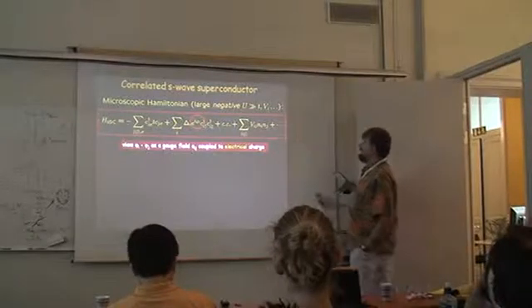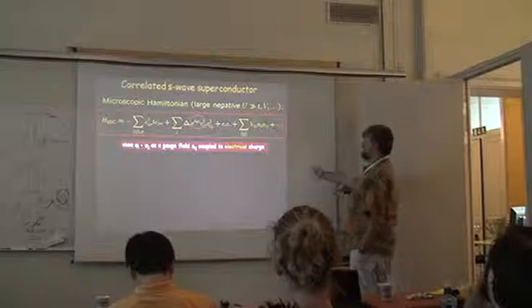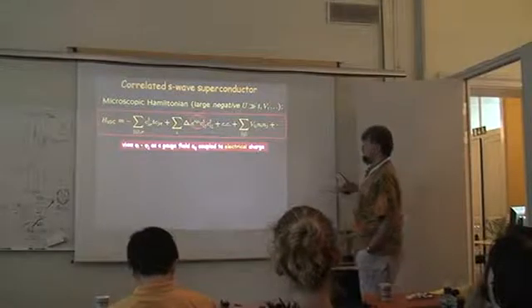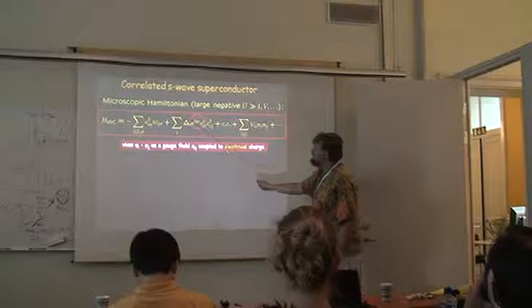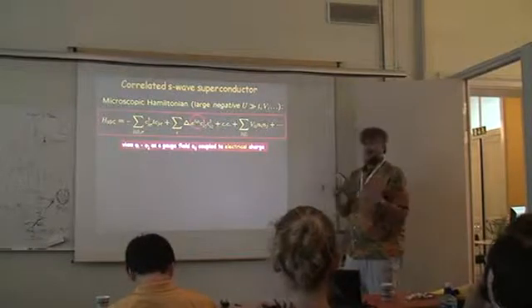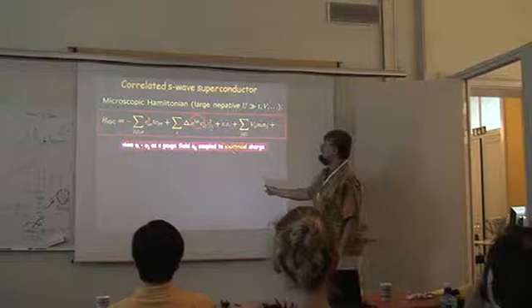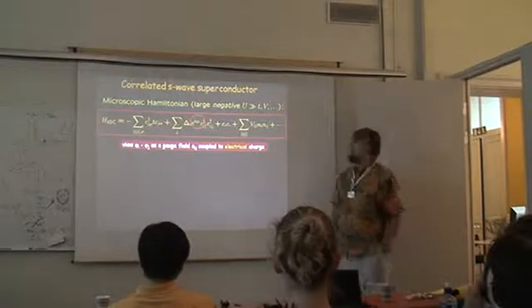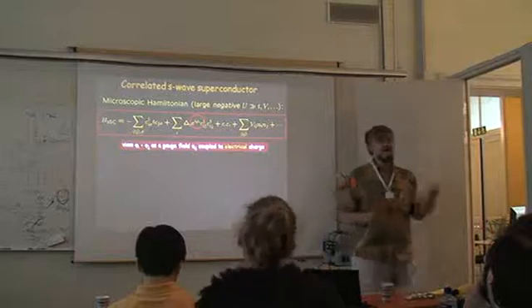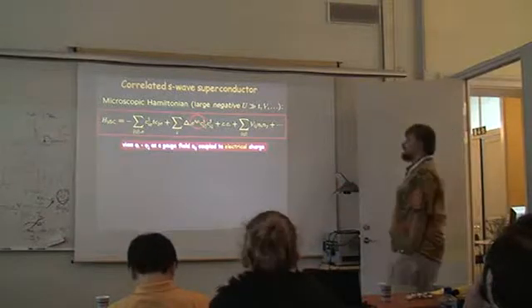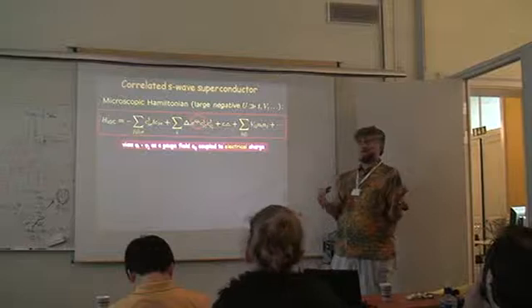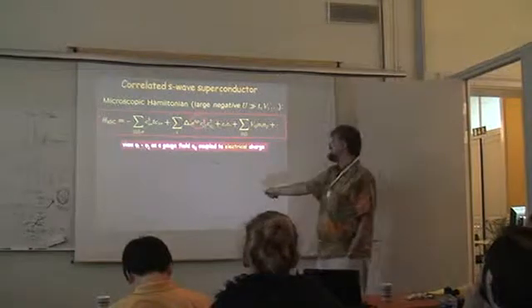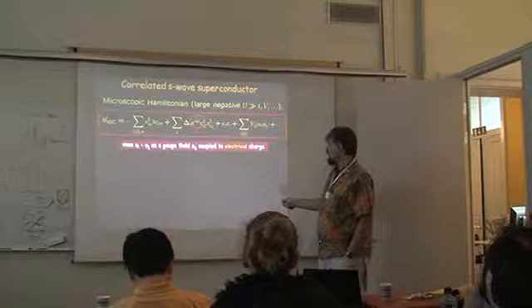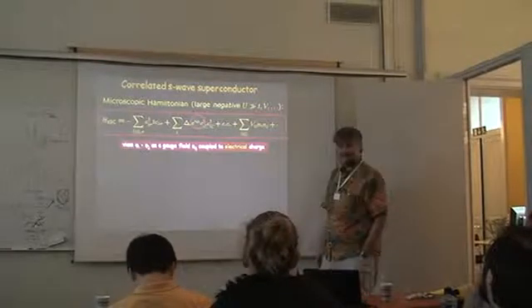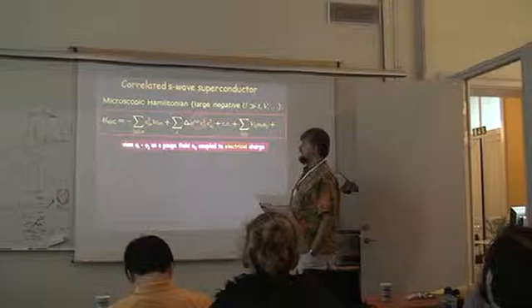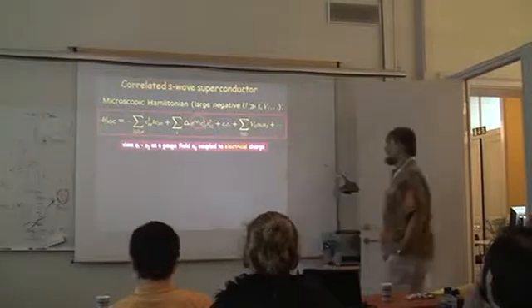So we can take now this very negative U Hubbard model where this energy is larger than any other energy, including kinetic and residual Coulomb interaction. We can then fix the amplitude of delta, which is like a gap parameter. We fix its amplitude, but leave its phase to hang. And fixing its amplitude is good because it always buys us this binding energy of minus U. Then we put a phase here. Then naturally we think of phi_i minus phi_j as a gauge field, which is coupled to electrical charge. This gauge field is on a lattice. Phi_i minus phi_j makes this gauge field compact. But that's okay, we know how to deal with that.